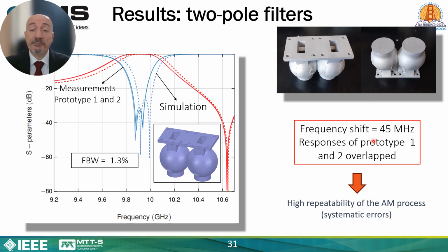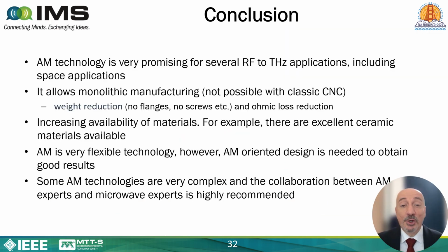As you can see, there is a frequency shift of 45 MHz, but we manufactured two prototypes, and as you can see here, the responses of the two prototypes are practically overlapped. This means that this process has a very high repeatability, and this means that this is a systematic error, and systematic errors can be easily removed. So, to conclude, additive manufacturing is very promising for several RF to terahertz applications, including space applications.